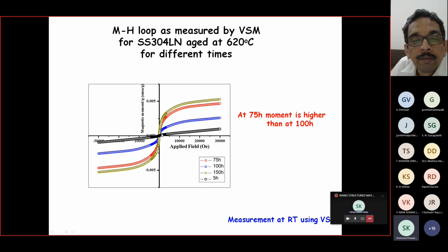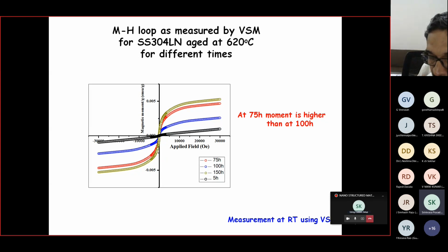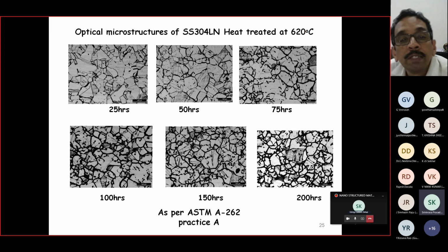Okay. Now, if you notice this particular thing, and if you see my color legend over here, at 5 hours it is still paramagnetic. It is still straight. But if I go to 75 hours, it is showing strongly ferromagnetic behavior. Then, if I go to 100 hours, you should expect that it should be still more ferromagnetic. But unfortunately, it is not more ferromagnetic, but the saturation magnetization has come down. And similarly, if I go to 150 hours, it is again going back. So this is something anomalous and a bit confusing. We wanted to examine what is the reason. And of course, still we have not yet established what is the size of the precipitate. Okay, so that is also one thing which is still remaining.